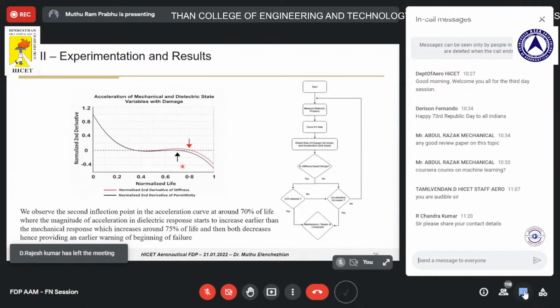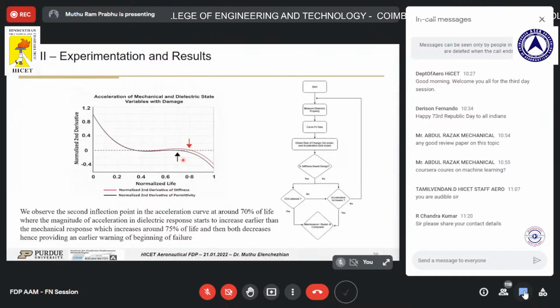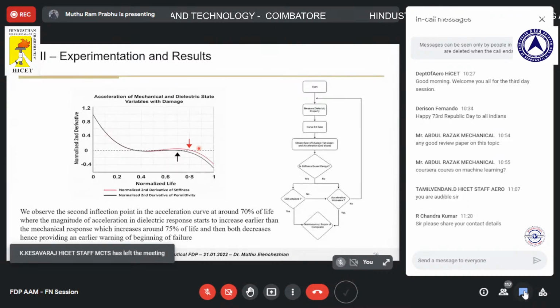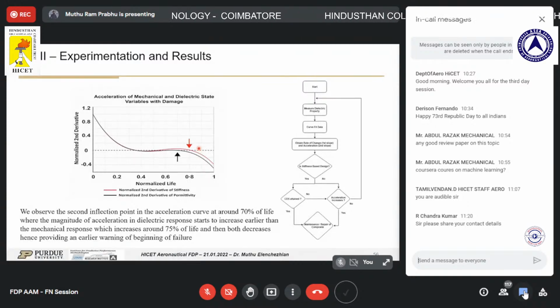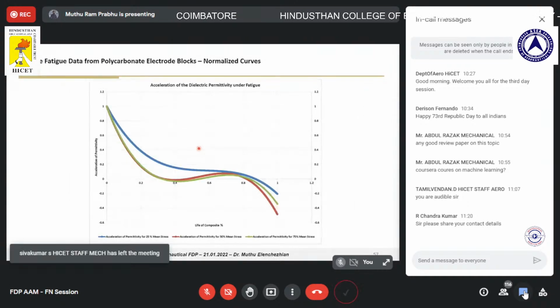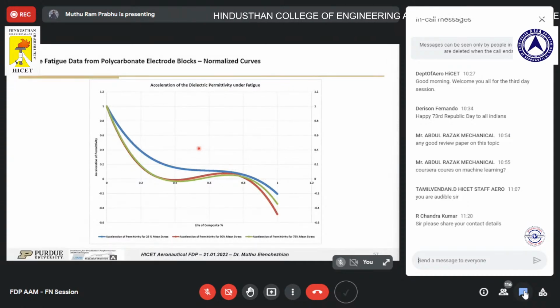That is, the permittivity curve was able to predict the failure in the material well earlier than the final failure actually occurred. The failure in the stiffness curve was obtained at 75% of life, but the permittivity data was able to predict it at almost 70% of life. And this is for one particular loading condition of fatigue. The same behavior was obtained for the other two loading conditions of fatigue as well, under 25% and 50% mean stress levels.